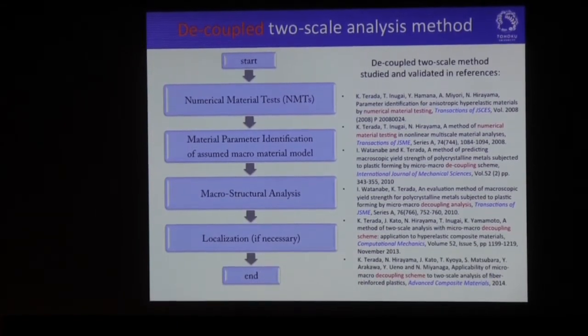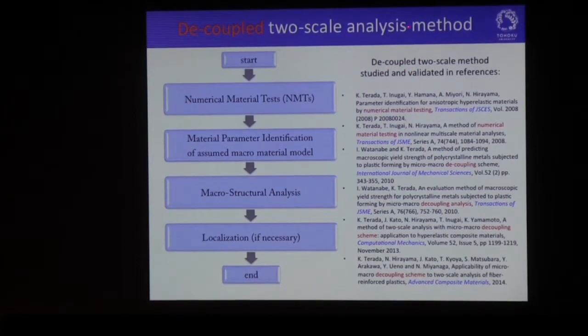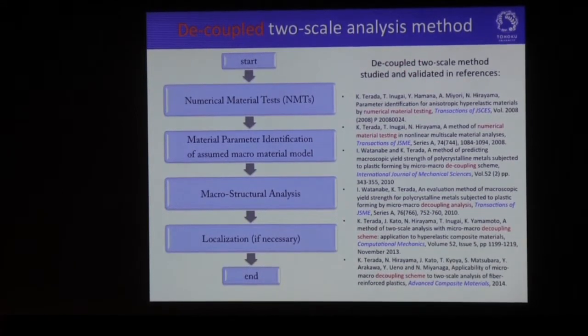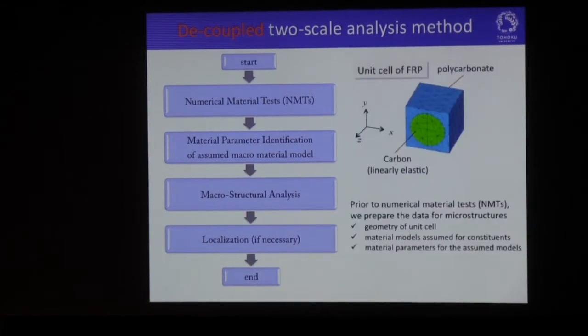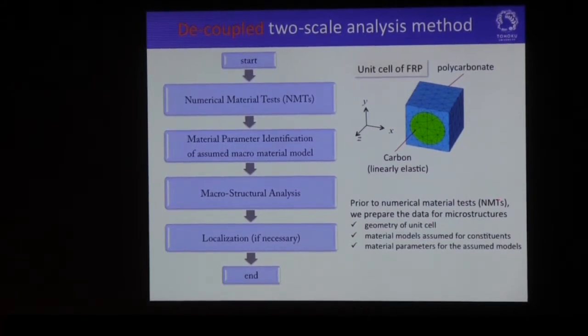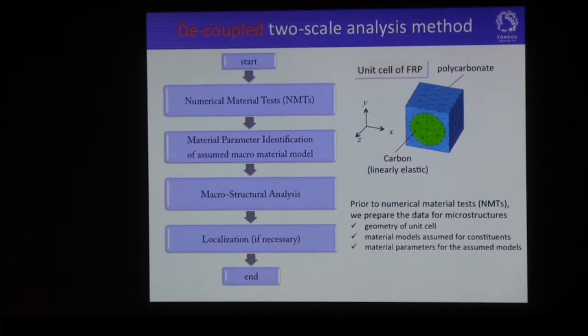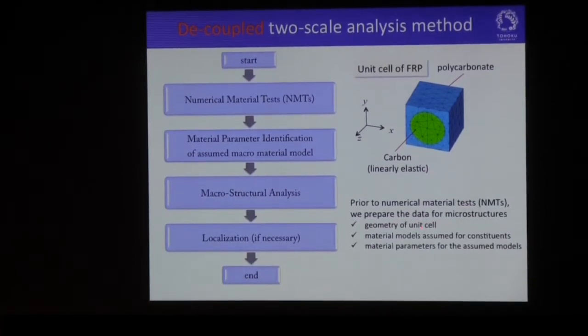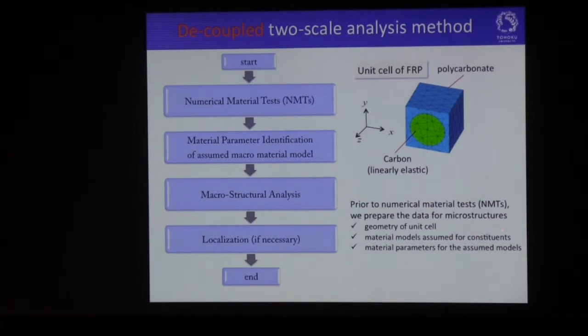But now I recommend the decoupled two-scale analysis method that is studied and validated in these references. Let me show you a very simple numerical example using this kind of unit cell, which is composed of the carbon fiber and polycarbonate matrix. Before conducting the numerical material test based on the homogenization method, we prepare the data for the microstructure, that is the geometry of the unit cell, a material model assumed for the constituent, and also the material parameters for the assumed model. We assume the carbon fiber is linearly elastic, but polycarbonate should exhibit some sort of nonlinearity.